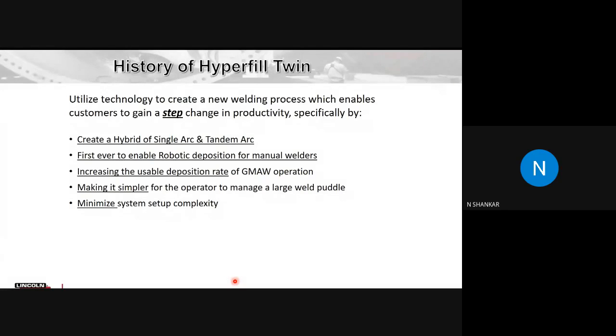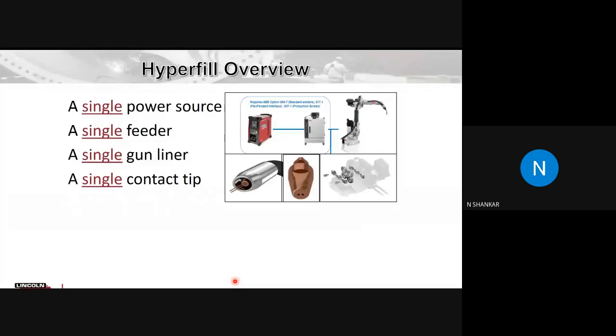It increases the deposition rate of the GMAW process more than twice, makes it simple for the operator to manage the weld puddle, which has been tested and proven, and also minimizes the setup complexity that comes with the tandem set. So where you have difficulty in terms of process or in terms of commercial viability, Hyperfill is a solution.